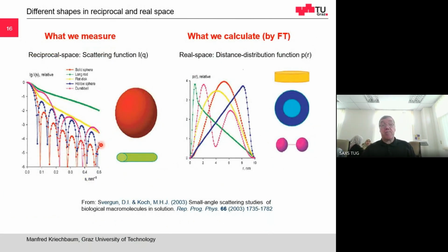Here again, in a static picture, for different sizes, for different shapes, the scattering, like if you have a very symmetric particle, you have a very sharp maximum minima, and if you have a very anisotropic nanoparticle, you have a very diffuse scattering. So how does it look like in the real space? The sphere has also a very symmetric P of R function. And the hollow sphere, in the hollow sphere, you only have large distances. So the large distances will have a maximum at the diameter of this hollow sphere. So this is this blue